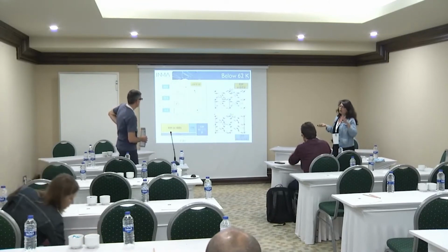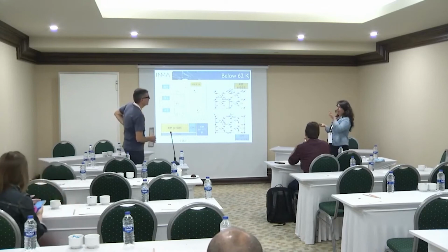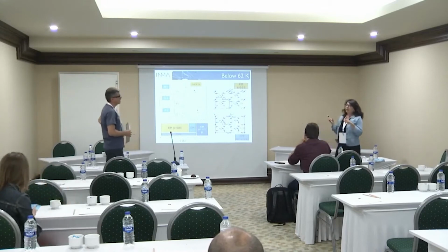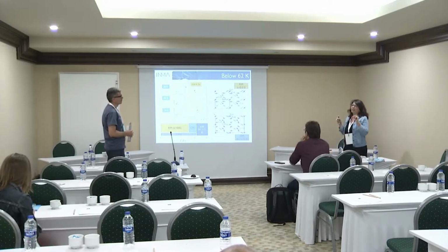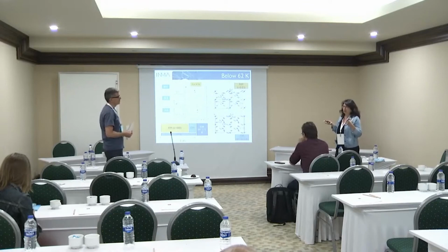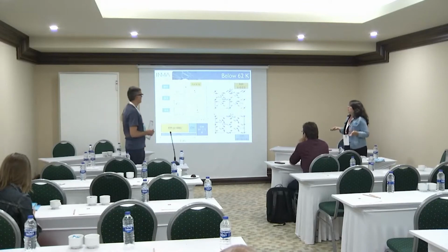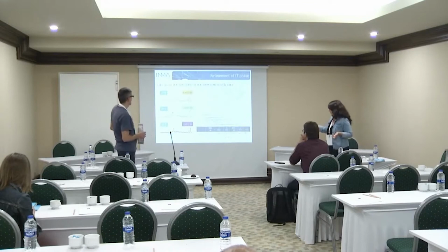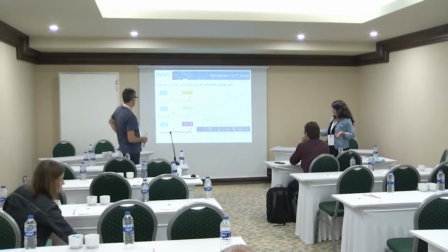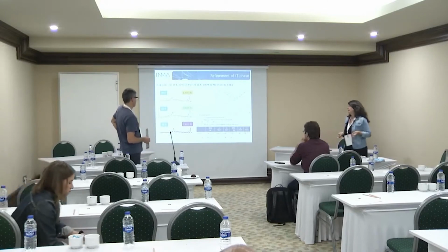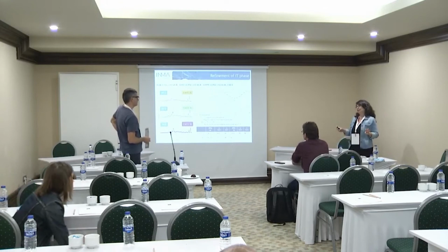But the charge order was proposed in the first publication of this structure, but it was based only on a difference of interatomic distances and it was not very robust. Some years later, people conducted more precise synchrotron radiation measurements, and they showed that you really can't justify a charge ordering scenario. You can see that there is a difference between the strength of the magnetic moments, but you can't really say that it's charge order.